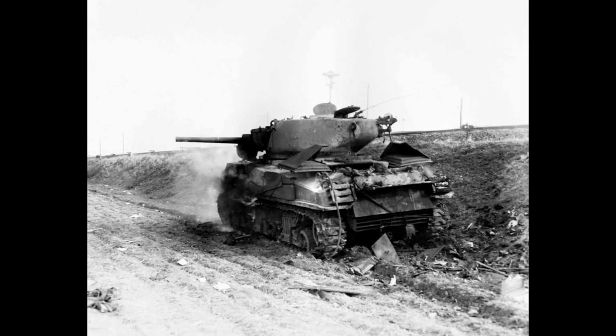Kowalski chose a compromise. He welded steel spacers at the top and bottom edges of the glacis, creating a 1-inch gap between the original armor and the added plate. This configuration served multiple purposes. The air gap would potentially disrupt shaped charge jets. The standoff reduced direct thermal transfer to the base armor during welding, minimizing heat stress. And if the added plate took a direct hit that caused cracking, the damage might not propagate into the tank's structural armor beneath. The welding process took 11 hours spread over 2 days.